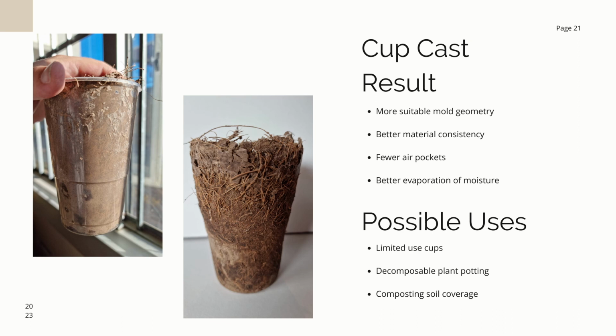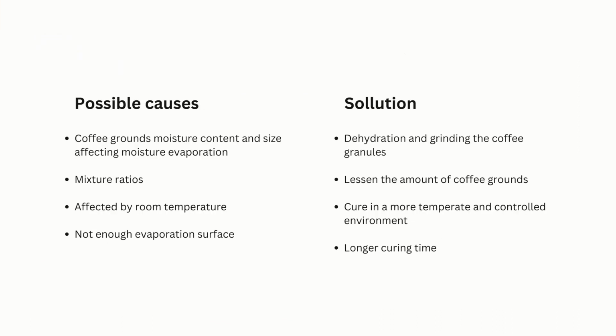Possible uses would be limited use cups, decomposable plant potting, and composting soil coverage. There are a few possible causes for not achieving the desired material in these casts. Solutions to these would be further dehydrating the coffee grounds and using finer ground granules, lessening the ratio of coffee grounds in the mixture, curing in a more temperate and controlled environment, and allowing the casts a longer curing